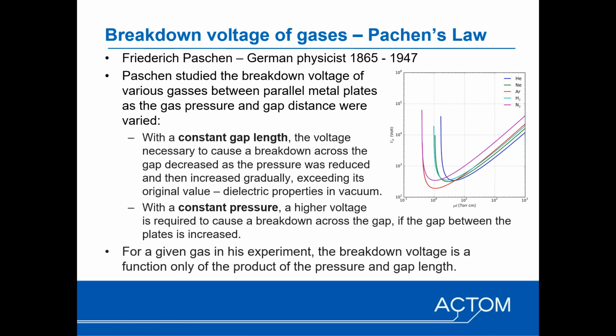One of the German physicists, Friedrich Paschen, did some studies of different gases at different pressures and the variation of the gap between parallel plates. And what he found is that at high pressure, for a fixed gap, you need to apply a high voltage in order for the breakdown to happen across the gap. As the pressure is reduced, the breakdown voltage is also reduced, which is the same mechanism as what I explained in terms of the Townsend.